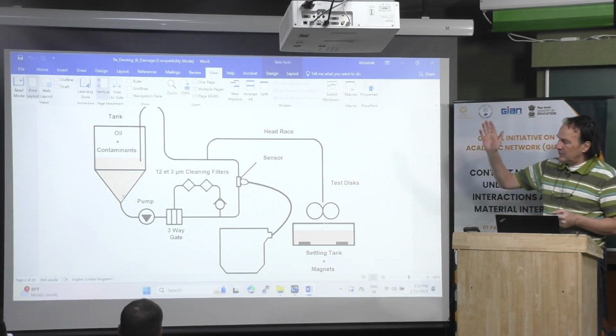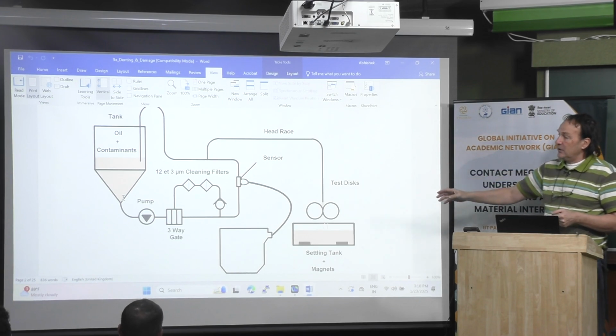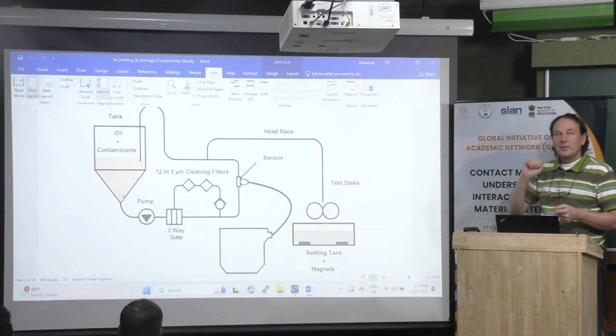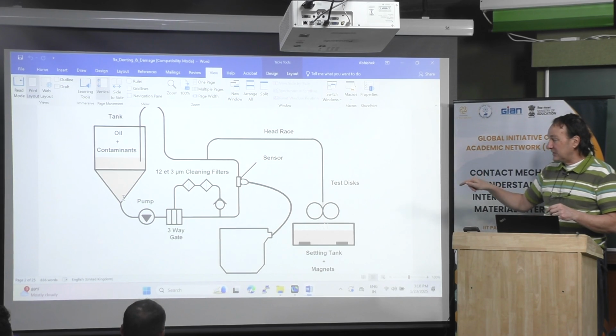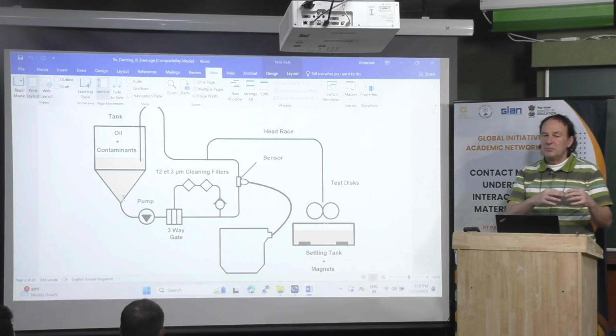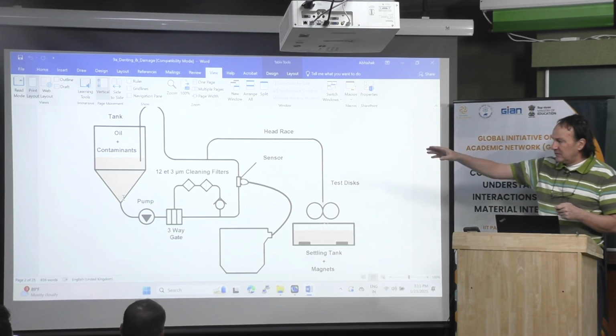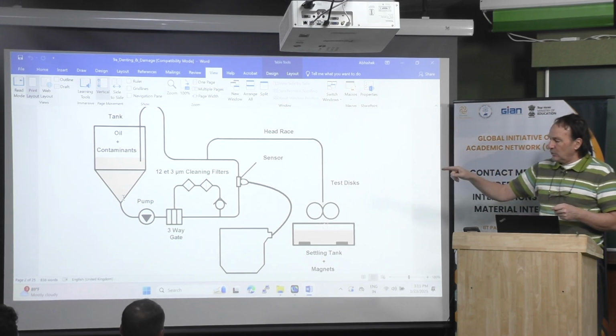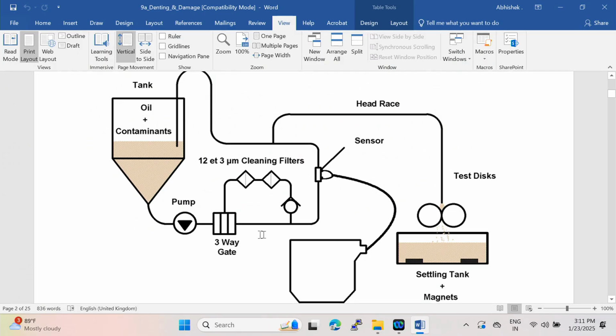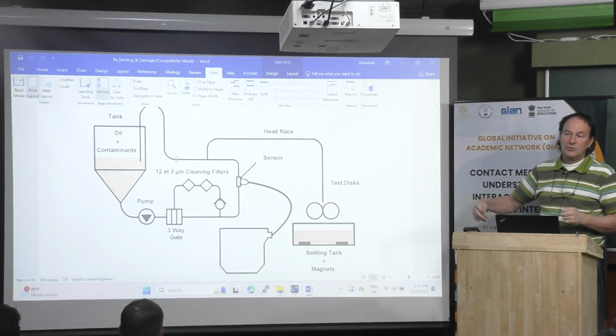Then the principle is to have some particles in the oil, and to have something without corners or things like that. So the particles should always be moving in the oil. There is no chamber where the particles can accumulate, for example. It means that everything should be conical, and all the pipes should have a flow within a turbulent regime. When it is turbulent, nothing will stick at the border of the pipe. Then it's very easy to calculate which size of the pipe you should use. You just have to know the flow with the pump, and then you manage to have a turbulent flow.